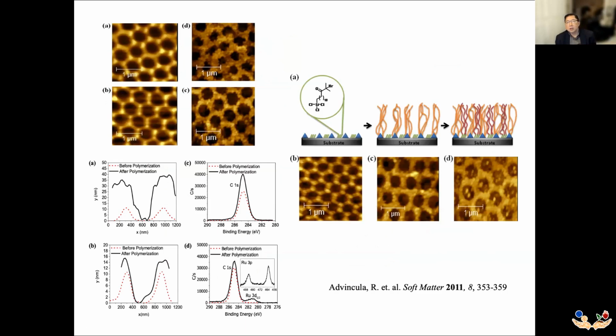So, for example, you can reverse the patterning where the initiators are grafted on the beehive pattern. And then as you grow the polymer, as you can see here, there's an increase in roughness on top of the pattern, also exposing the inner part of the beehive structures, again amenable to grafting an initiator and then growing a polymer brush. So in this case, we have a ternary composition made up of the conducting polymer, the polymer brush that was first grown on the ridge pattern, and another polymer brush that was grown inside.